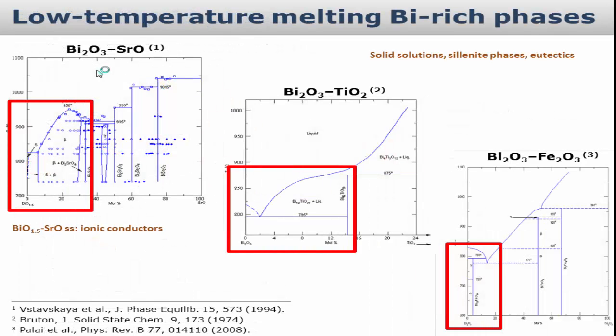So sometimes it's useful to check this when you work with such complex systems. You don't have all the phase diagrams, but it's instructive to check the binaries, for example, in this case between bismuth and strontium, bismuth and titanium, and bismuth and iron oxide. And you see that you have at least three things that might be critical when you try to synthesize this material. For example, in the case of strontium oxide, you get solid solutions, which will vary in melting temperature as a function of strontium content in the solid solution.